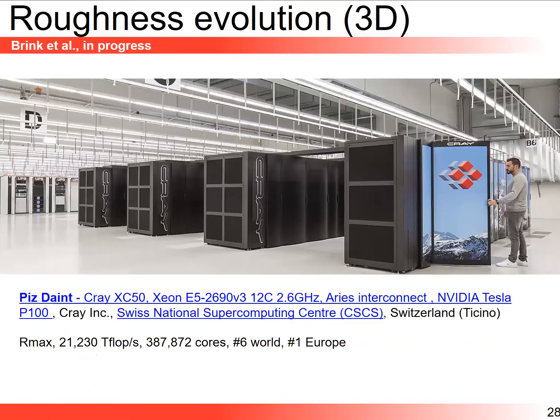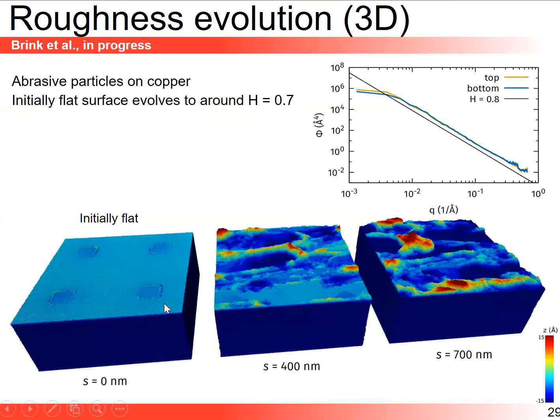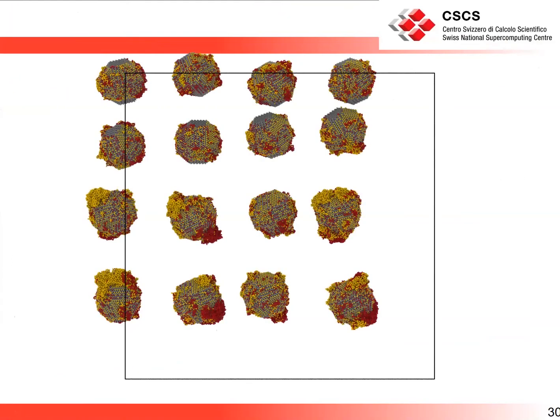We are also trying to finish extracting data, and I will not cover this again, but just a teaser slide where we move from those 2D simulations to really 3D simulations we could access at the time, on what was the fastest supercomputer in Europe. Now I think it's number 3. It's located in Switzerland, in Ticino canton. And with this, we could look at roughness evolution in a 3D setting. So you see that here, starting from something flat, we arrive at something rough, with again evidence of some self-affine scaling for the surface. And we've also looked at interactions between debris particles. Here we're looking down at the interface, and those are particles that, as they move along the surface, because of adhesive forces, are going to accumulate mass.